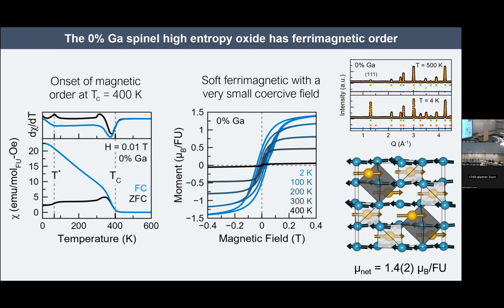And then we can perform a symmetry analysis to actually refine the sublattice moments involved. And we get out what we expected, which is a ferrimagnetic arrangement where my tetrahedral moments and octahedral moments are anti-parallel to one another. And what was very satisfying is that the saturated moment that we see from magnetization is in beautiful agreement with the calculated moment from the neutron diffraction.